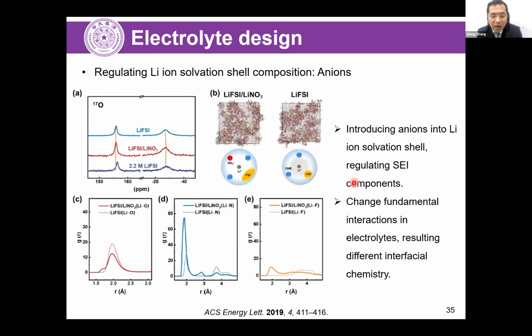And in fact, if we try to analyze the reaction, it happens between the lithium metal anode and the ion complex. So if we try to introduce the electrolyte with different ions, for example, as we mentioned before, nitrate ions prefer to attach to the lithium ion. So in this case, once we introduce nitrate ions in the electrolyte, it is found that the peak shifts in NMR, in the oxygen peak, can be observed.